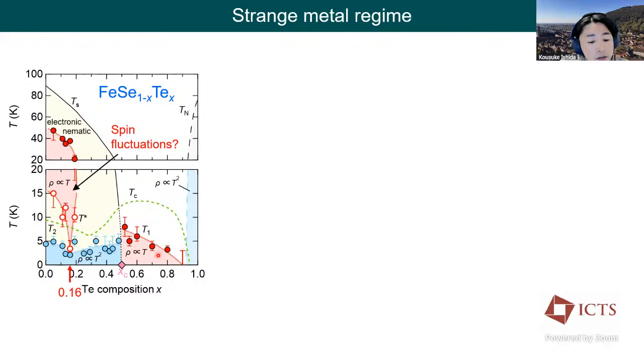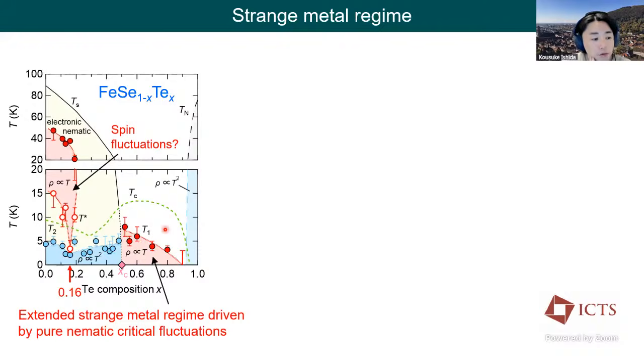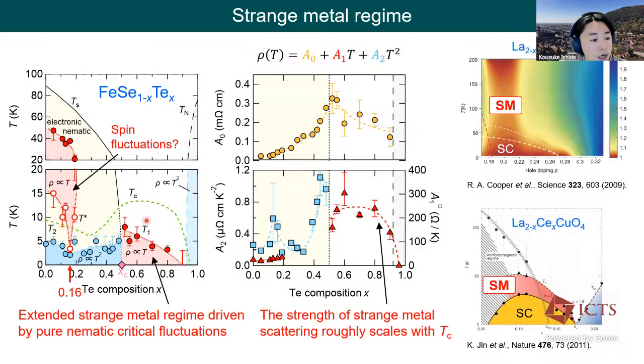And the other is outside of the nematic phase. The onset of T-linear resistivity, T1, increases with approaching the nematic QCP. So the leading candidate for the origin of strange metallicity here is enhanced nematic fluctuation at these low temperatures. And furthermore, the T-linear coefficient roughly follows Tc. This points to a close relation between strange metal scattering and electron pairing.